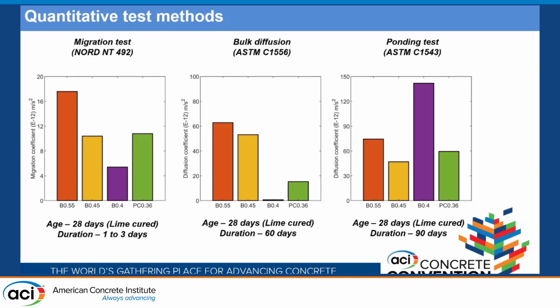And for the ponding test you have a duration of 90 days. One thing with BCSA cement is that it hydrates at later ages as well. So you have a cement that is hydrating, and that seems to have an influence on the diffusion coefficient.